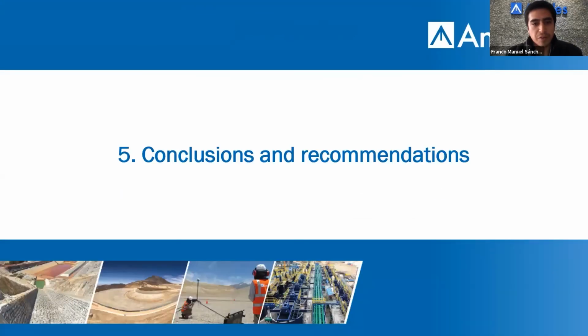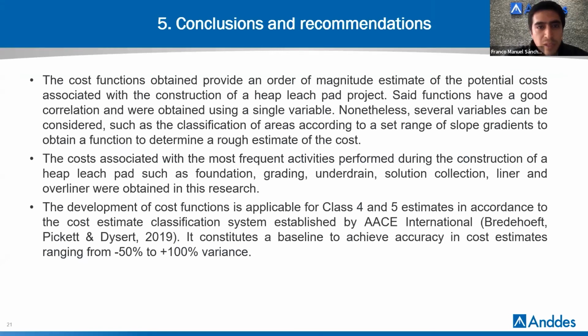Okay, conclusions and recommendations. The cost functions obtained provide an order of magnitude estimate of the potential cost associated with the construction of a heap leach pad project. These functions have a good correlation and were obtained using a single variable. Nonetheless, several variables can be considered, such as classification of areas according to set ranges of slope gradients, to obtain a function to determine a rough estimate of cost. The cost associated with the most frequent activities performed during the construction of a heap leach pad, such as foundation, grading, underdrain, solution collection, liner, and overliner, were obtained in this research.